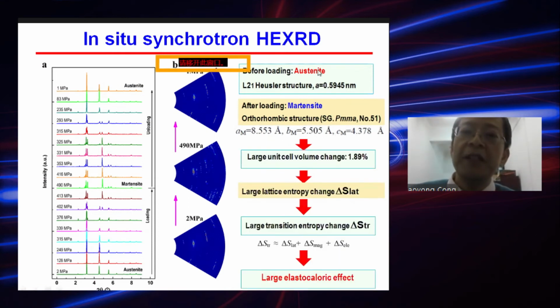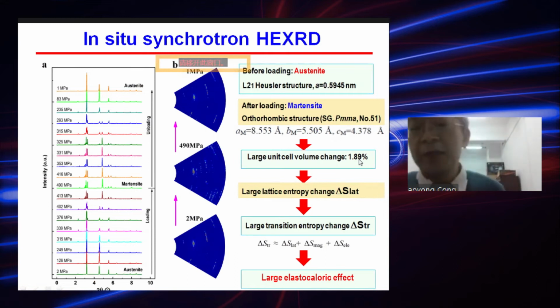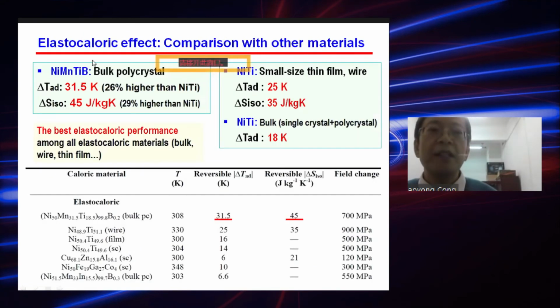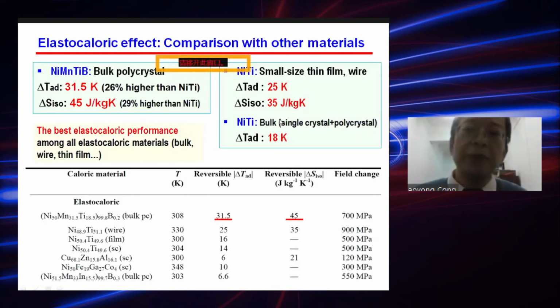With the lattice parameters of austenite and martensite, we get a large unit cell volume change of 1.9%. This leads to a large lattice entropy change and thus a large transition entropy change. And finally, we get a large elastocaloric effect. Now we compare the elastocaloric effect in our material with other elastocaloric materials.